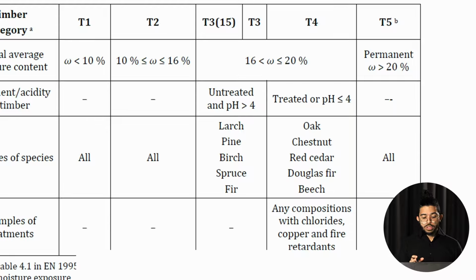In most cases, if you are in a full indoor environment or in an outdoor but protected environment, you cannot do this further, deeper analysis into the species. If you are in service class 3, though, you have to check the species and their acidity. So in the T3, you will see the most common species, larch, pine, birch in construction, and they have a pH above 4. Less than 4 would be considered T4, and most of them are hardwoods, and they are what we should consider aggressive timber. So it's oak, chestnut, cedar, Douglas fir, and beech.